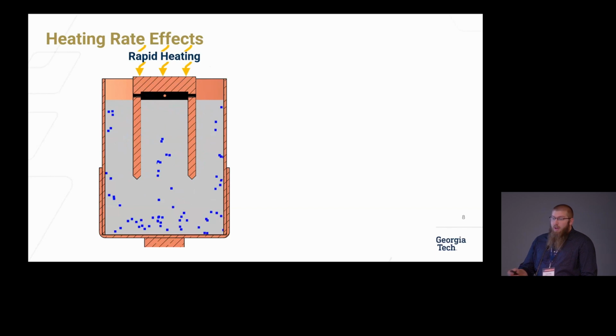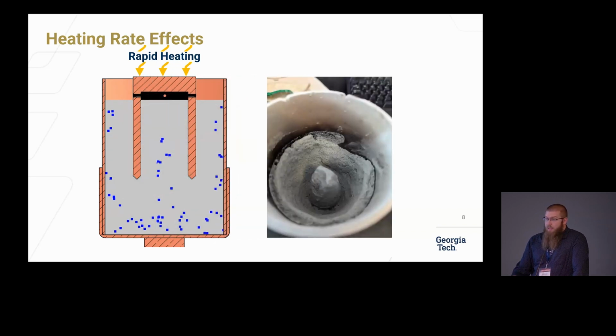And the reason we believe this is that when you have a rapid heating rate, you have quick sublimation around the heating element, which leaves this desiccated layer of dry regolith. And this dry regolith, which is porous, especially in a vacuum, is an excellent thermal insulator. So it prevents the heat from transferring to the rest of the packed bed, leaving the rest of it icy. We've actually shown this in some of our experiments, where you can see the walls in the center of the packed bed are still frozen, while the regolith simulant that was around the heating element has been desiccated and removed.